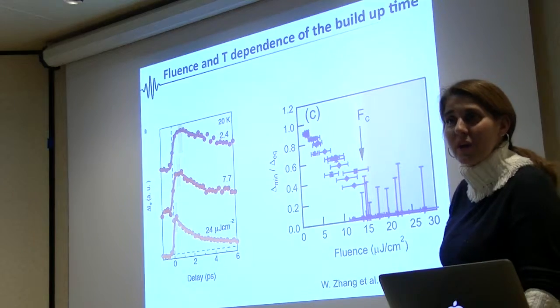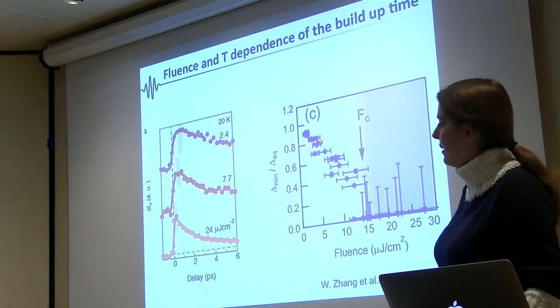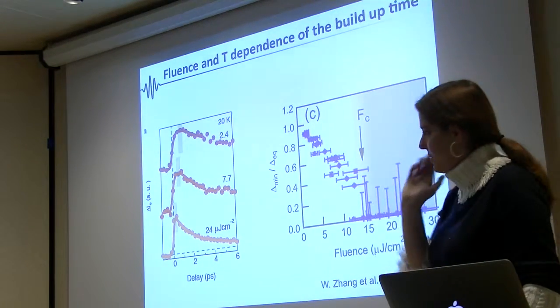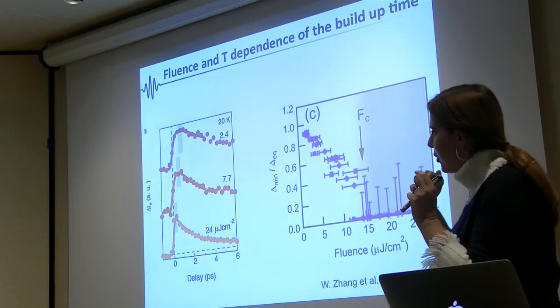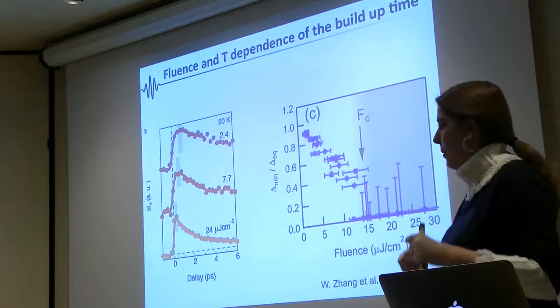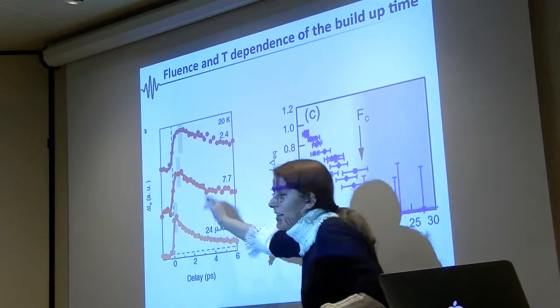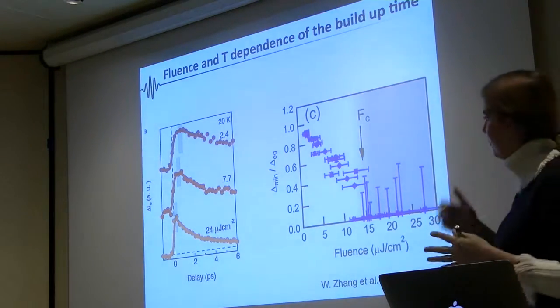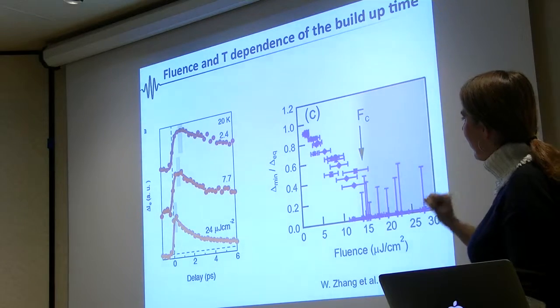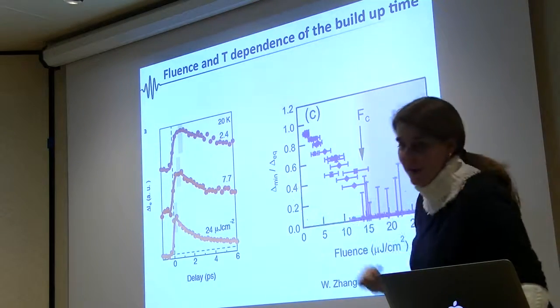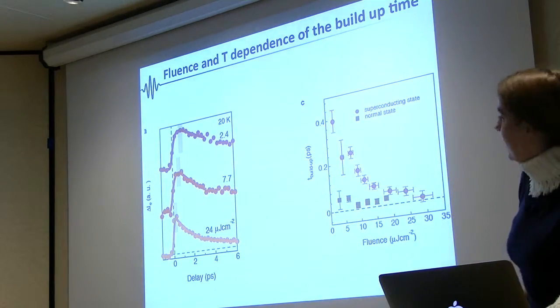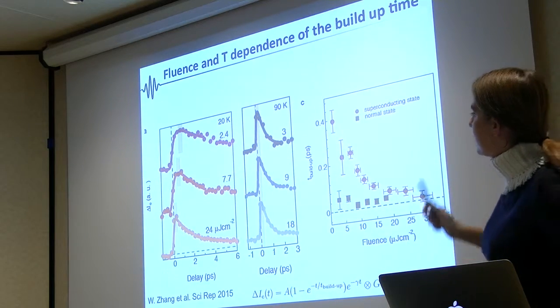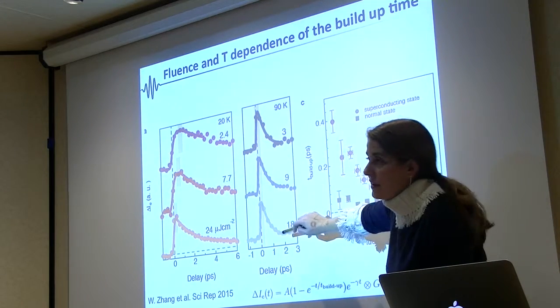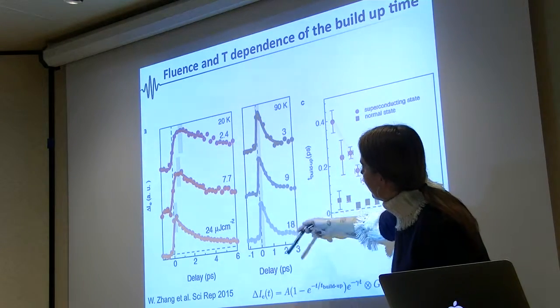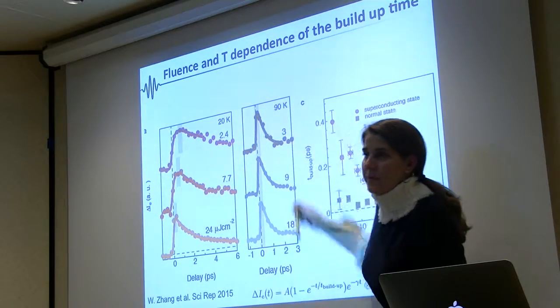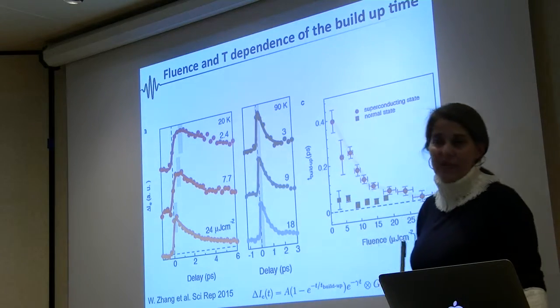As Stefano talked about topological insulators, we have several papers on that. The response is immediate. You do this, you have immediate response, although if you have your sample prepared in a certain way, you see that this peak can finish all the way up. And this is because of Fano and some other dynamics. But, going back here, we are learning this effect. So then we can do the same thing in the normal state. And again, this is what I told you before. There is no build-up time, the response is immediate, no matter how much energy you are delivering to the system.